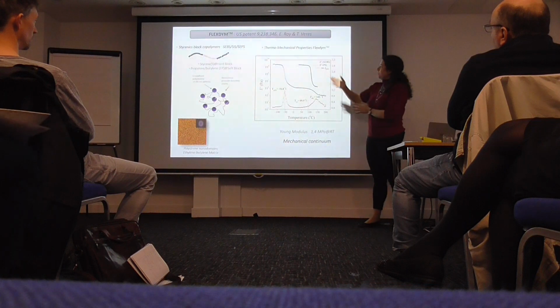It has the same mechanical properties as PDMS, because we have to admit that PDMS is really cool. One thing that we didn't realize with PDMS, and we didn't realize until we started selling that stuff, is that the fact that PDMS is flexible makes it really easy to adhere. So if you're thinking about two petri dishes and you try to bond them, because they're rigid, they're never going to conform 100%, but PDMS, because it's soft, you can actually make sure it's bonded against it. When we started coming out with those, we had a couple of industries that came and told us, oh, cool, we're going to be able to use it as a sealant, because they were having trouble bonding two different plastics, and they started using our material as the sealant in between, because it conforms really nicely. So that's something we didn't realize until we started selling it.